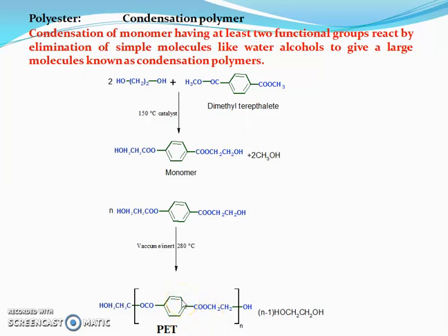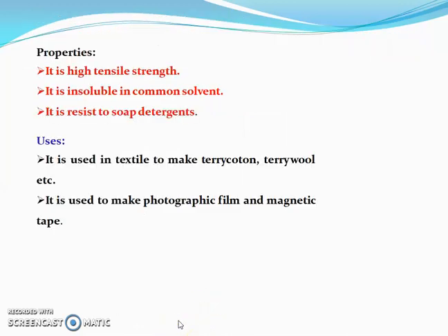The ethylene glycol molecules are eliminated during the ester exchange reaction. The molten polyester can be extruded into filaments, which are spun into a fiber and stretched by 3 to 6 times the original length. And we get terylene polymers. Now we are going to discuss their properties.